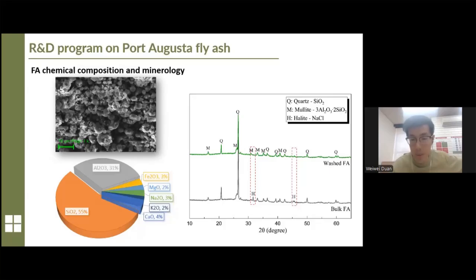It's very typical crystal phases we can find. The first one is the quartz, which is very typical in fly ash, and the mullite, also very typical in fly ash. And the difference is the highlight. That one, we believe, is from the seawater. So after we wash the fly ash, that one cannot be detected in the XRD results, which indicates an efficient washing process of the Port Augusta fly ash.